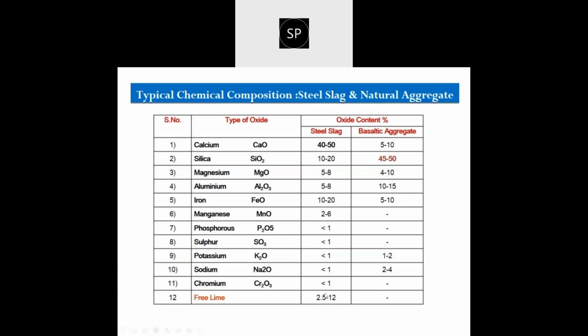Now, one of the important characteristics is the presence of free lime, and this quantity of lime may pose volumetric expansion in the steel slag aggregate. The presence of free lime is significant, particularly in the steel slag obtained from the basic oxygen furnace process.